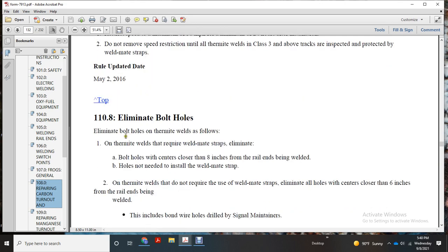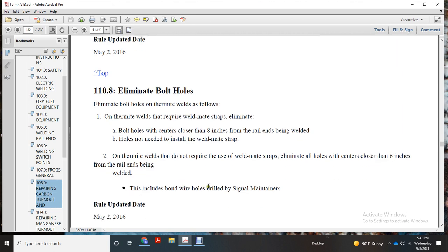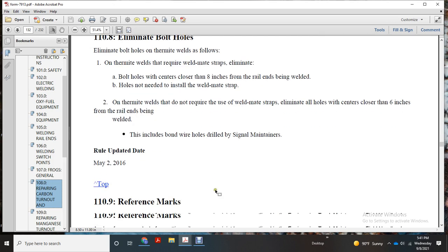Eliminate bolt holes of thermite welds as well. The thermite welds are required with a weld mate strap. Eliminate bolt holes with the center closer than 8 inches to the rail ends being welded. Holes need not be eliminated with a weld mate strap on thermite welds that do not require the use of the weld mate strap. Eliminate all holes with the center closer than 6 inches from the rail ends being welded. This includes bond wire holes drilled by signal maintainers.